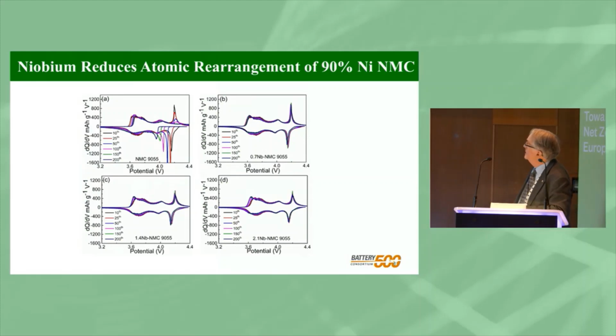And you see that same way if we do these electrochemical plots. Here, this is dQ by dV, so it's capacity versus the voltage. And you see with no niobium, this shift of these redox peaks is continuous cycle to cycle. By the time we got to 2%, these stay exactly on top of each other all the way from the 10th to the 200 cycle. So clear again, stabilizing the lattice.